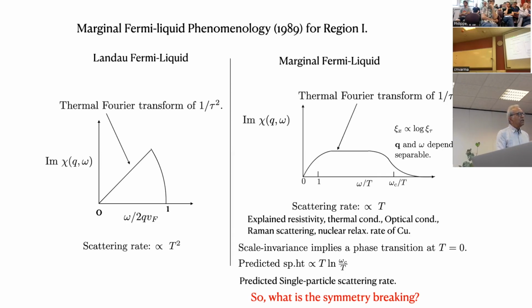And it is possible to show very easily, at least perturbatively, that the scattering rate from this will be proportional to omega over T, and if one believes again that there is Umklapp scattering modulo a coefficient, and it has taken me 20 years, 25 years to calculate that coefficient, I'll show you the result, how the resistivity is related to the scattering rate, and all these properties that are observed follow. Now, there's a very amusing mistake here, which was rectified much later and we had a microscopic theory for this.